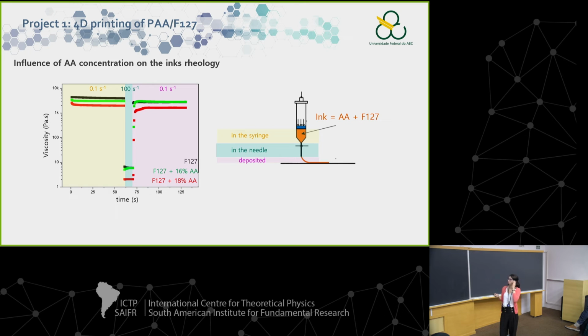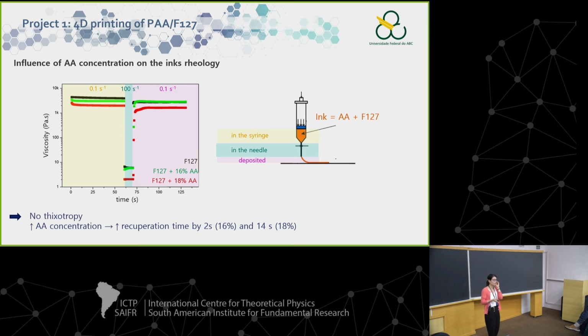Very quickly, another test that we perform is to mimic the shear rate that the ink will experience during printing. At the beginning, it is at rest, so a very low shear rate. Then it experiences a large shear rate, and then a low shear rate again. We look at this viscosity profile. We observe that we have no thixotropy; there is no change of viscosity with time. We also look at the time required to reach this viscosity. In the case of the 18%, the time to reach this high viscosity is 14 seconds, so it can impact the shape fidelity.